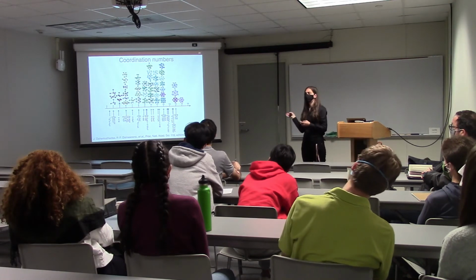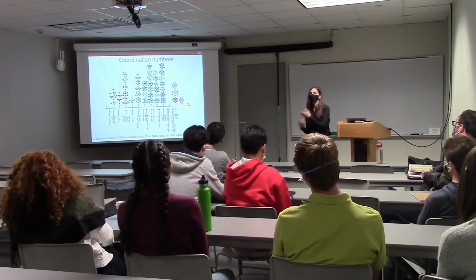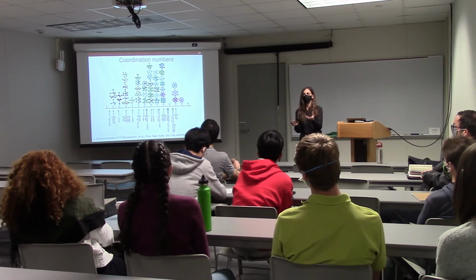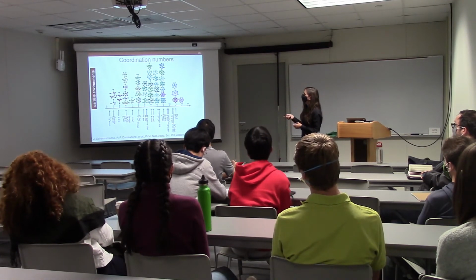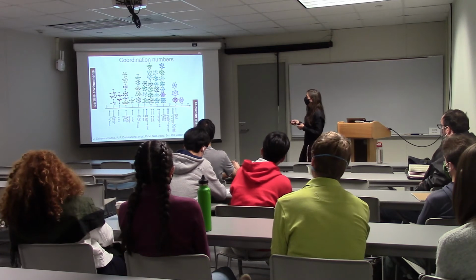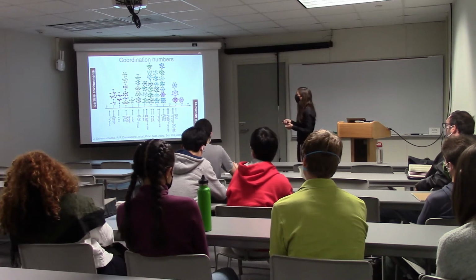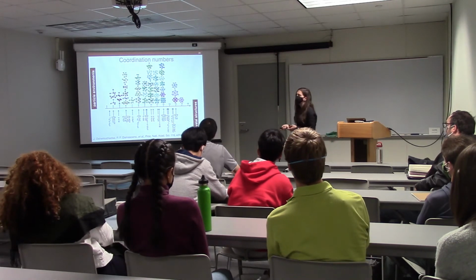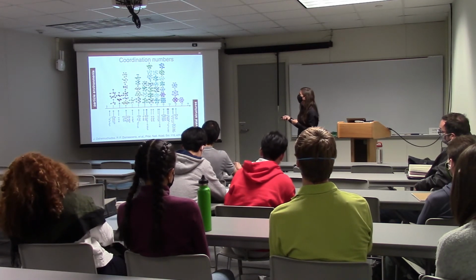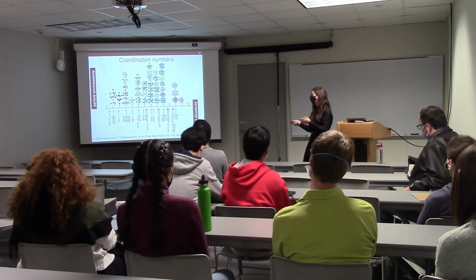And it starts making sense if you look at the coordination numbers. So if you look at it as a chemist, which I'm not, and I know that some of you are not either. But if you just look at how many nearest neighbors each particle has, at the top I'm showing you the particle environments, and at the bottom the crystal structure types. Aligned is by coordination numbers, so up here they're discrete because each particle environment just has an integer number of neighbors. But down here, these are rational numbers because these are all periodic crystals, but basically you can have any amount of neighbors on average because you can have different environments formed in crystal structure.